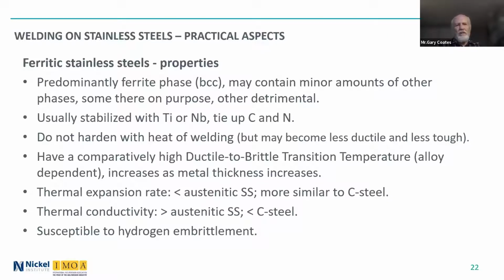A truly ferritic stainless steel doesn't harden with the heat of welding, although it may become less ductile and less tough. They have a comparatively high ductile to brittle transition temperature, which is alloy dependent. Sometimes it can be minus 30, minus 20. Other times it's around room temperature, and that ductile to brittle transition temperature can be even above ambient temperature. So you have to use them very carefully when you get into colder environments.